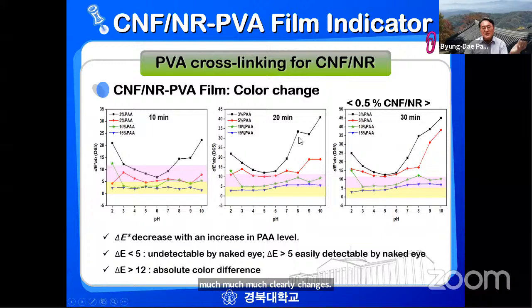And at 20 minutes also there are big changes in the 3% PAA cross-linker. There's a little change at 5%, and at 30 minutes, half an hour, much more color change in the 3% PAA and 5% PAA, depending on the pH, below pH 5 and above pH 7, they are changing colors. As I mentioned here, below 5 of delta E you're not going to see any change in color with the naked eye. But above 5, you can see the color change with the naked eye. So that means we can check all of these color changes with the naked eyes.